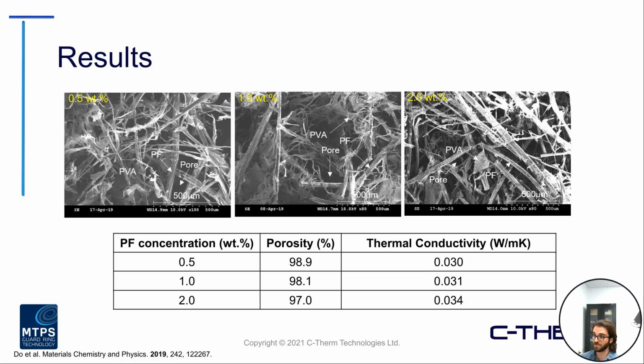Now, some of the results that were obtained, you can see up top the SEM imaging at different weight percentages, so 0.5, 1, and 2% weight loading of the pineapple fibers. As you can imagine, the increasing fiber concentration essentially resulted in a decrease in overall porosity. Basically, the more of that fiber was present, the more material was available to fill in that interstitial air, again, pushing some of that air out.